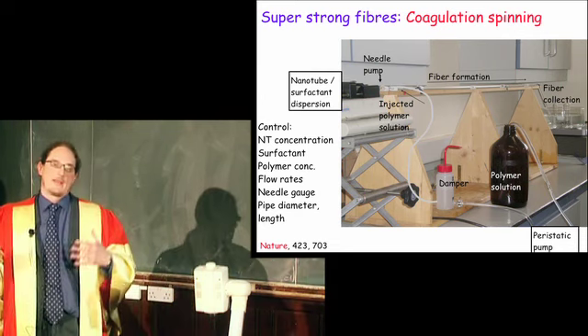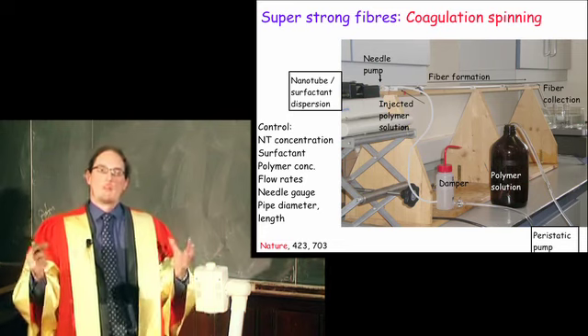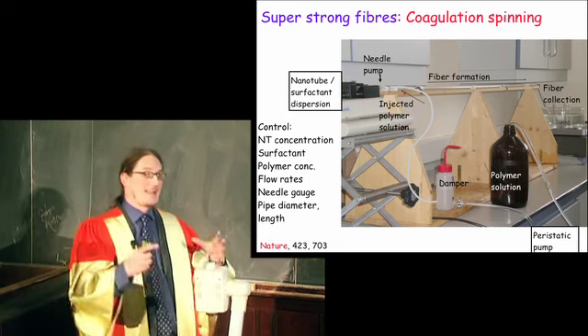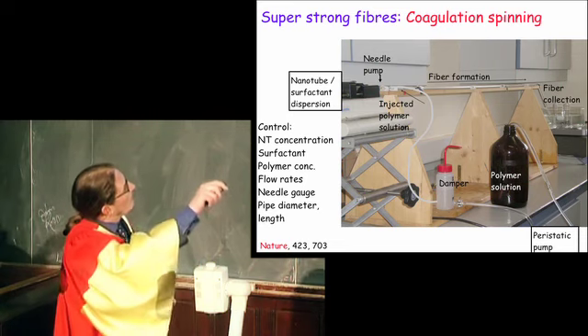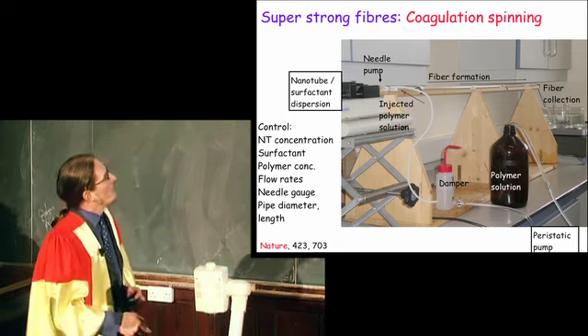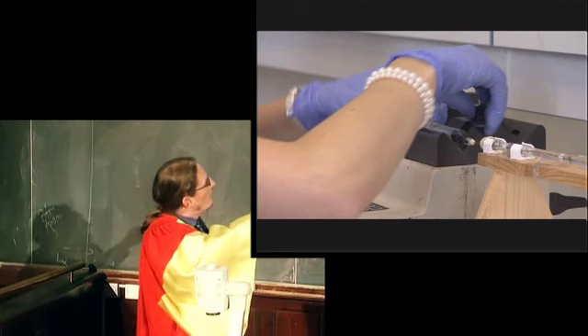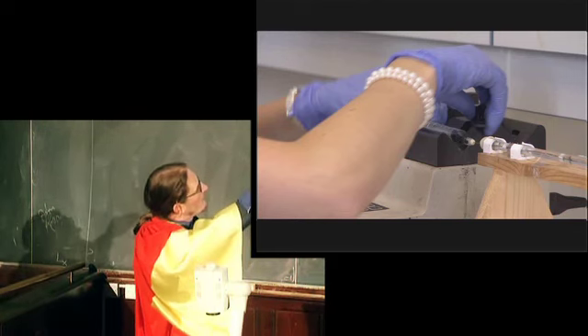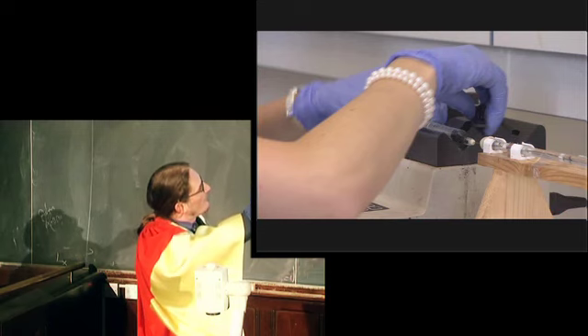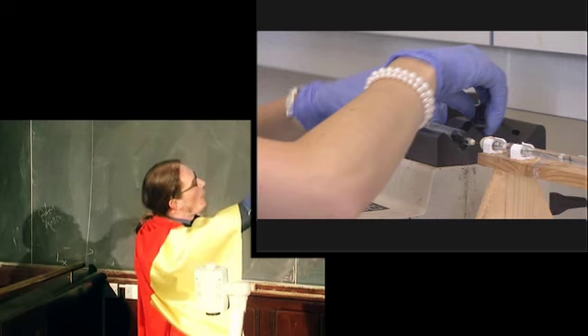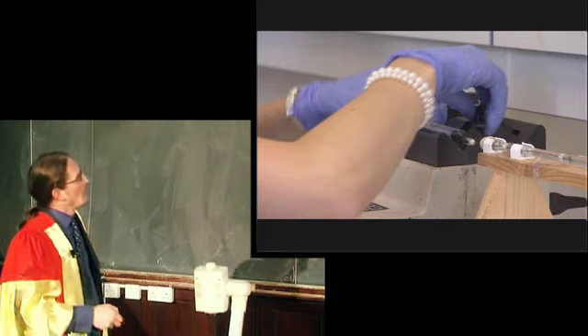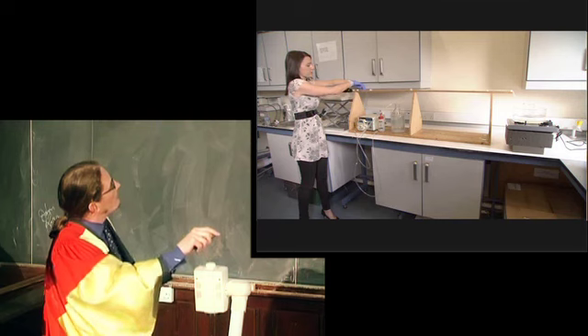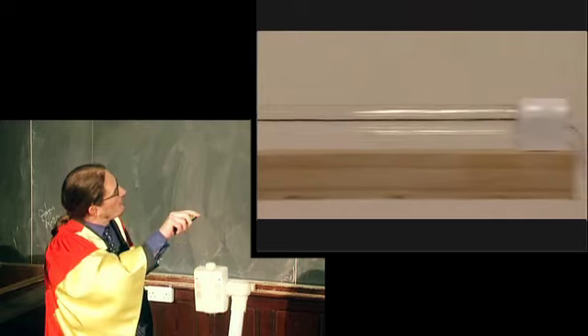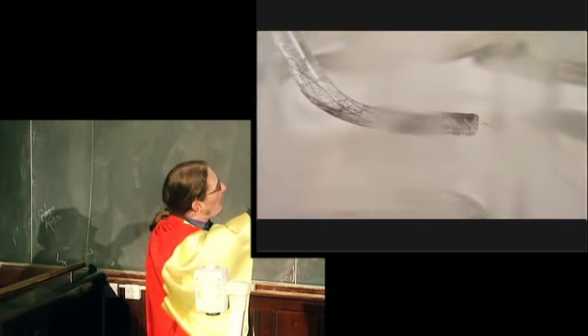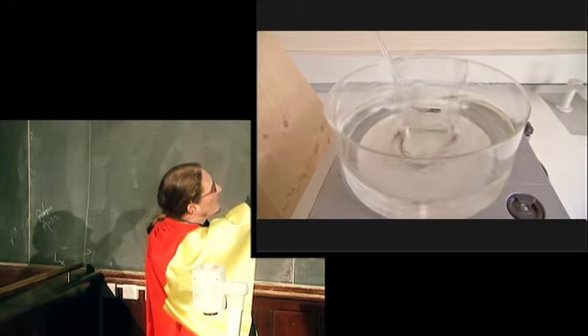What happens is, when the nanotube dispersion is exposed to the polymer, it causes the dispersion to destabilize and collapse to form a fiber. The fiber flows down the tube and is collected down here. Just to show you, this is Karen, who's in the audience, loading up the syringe with the nanotube dispersion, which will then be injected into this tube where polymer solution is flowing. When she turns it on, this is the fiber. It is formed almost immediately. It flows down the tube, goes into a bath where it flows around, and you can see it coming out and being collected on these mandrels.